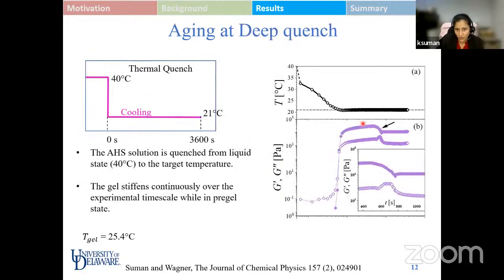a deep thermal quench. In the deep thermal quench, we follow the same protocol of taking the system at 40 degrees, the liquid state, and subjecting it to a thermal quench well below the gel point temperature. In this case, I subject it to 21 degrees centigrade, which is around 4.4 degrees below the gel point temperature. The temperature evolution which is happening experimentally is seen in the top figure over here, whereas the corresponding evolution of the modulus is seen in the bottom figure.